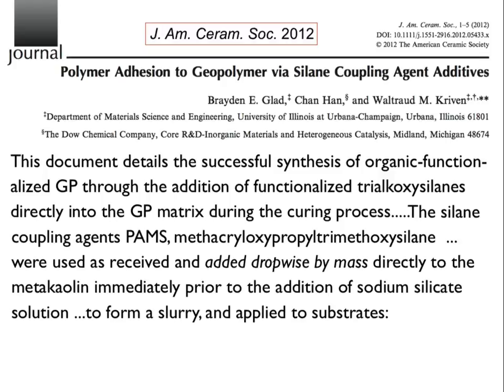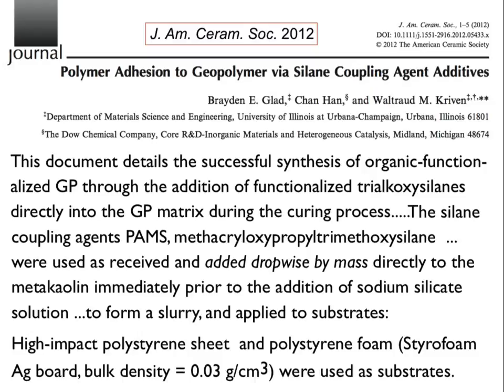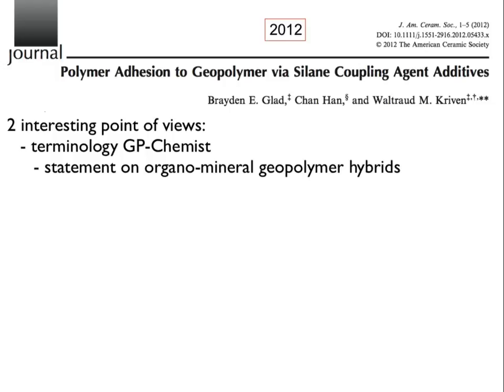The silane coupling agent, which is methacryloxypropyl trimethoxysilane, was used as received and added dropwise by mass directly to the metakaolin immediately prior to the addition of sodium silicate solution to form a slurry, and applied to substrates. And they used as a substrate high impact polystyrene sheet and polystyrene foam. So this has been geopolymer on polystyrene foam. The results are good, but for me what was important is something different.